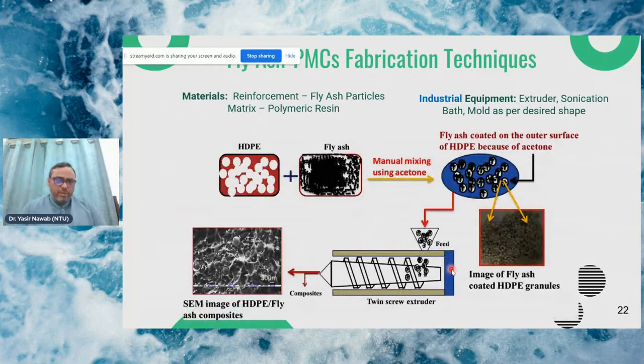So the first example that I'm going to share with you is high density polyethylene polymer mixed with fly ash. It's a thermoplastic polymer. The fly ash was mixed in acetone so that the dispersion can be made. There was a coating of fly ash on the particles of high density polyethylene. Then these particles coated with the fly ash were fed into the hopper of a twin screw extruder, and then we get the films which were ultimately converted into the composites. So using this method, the dispersion was very good.